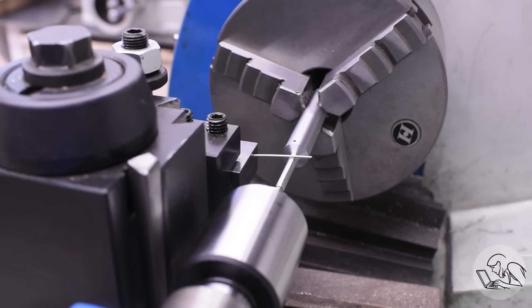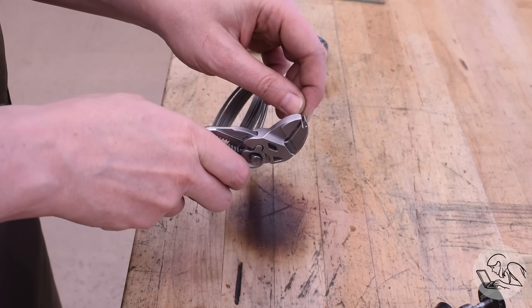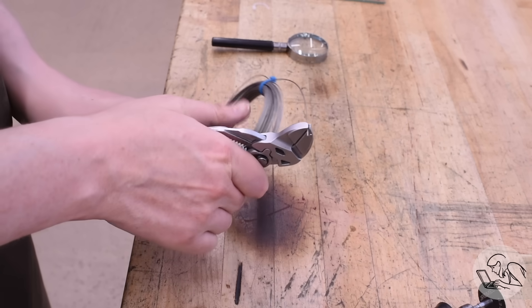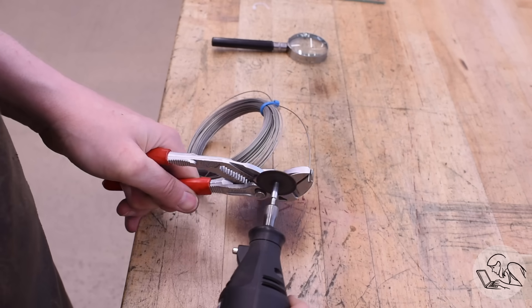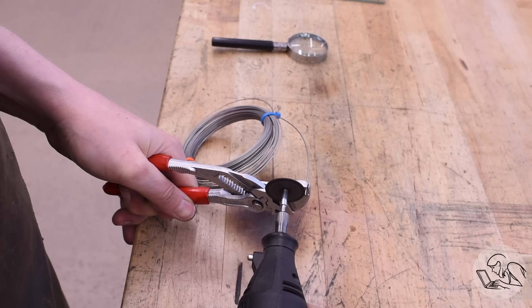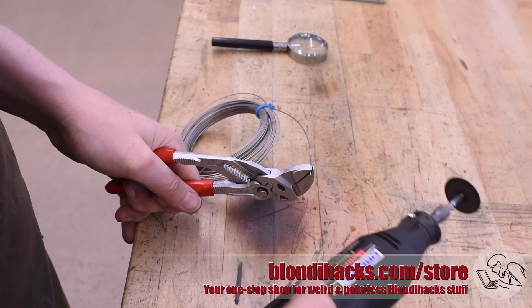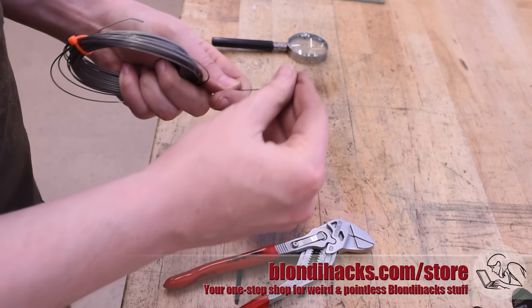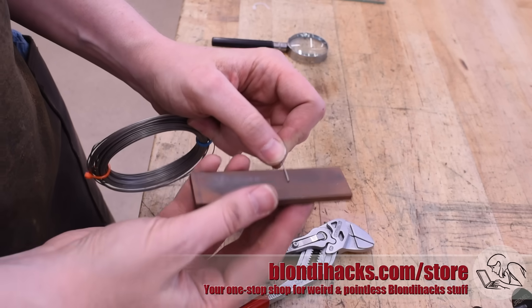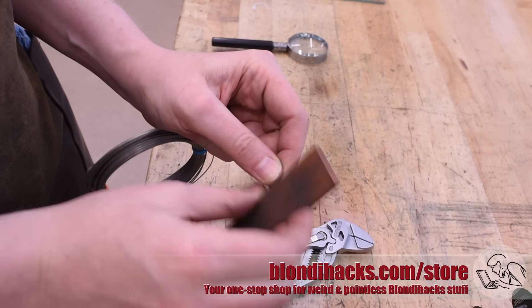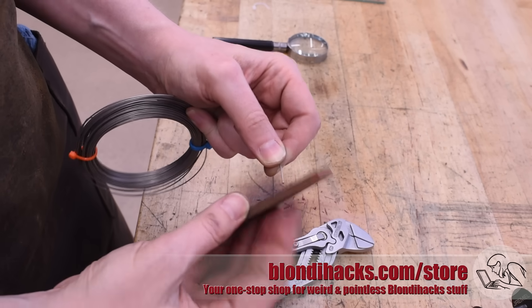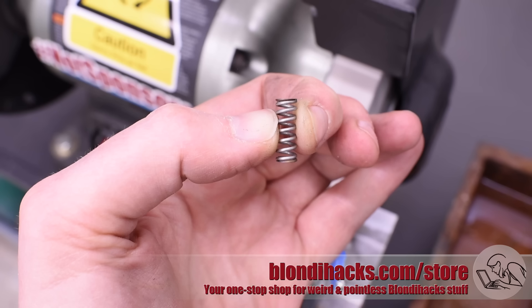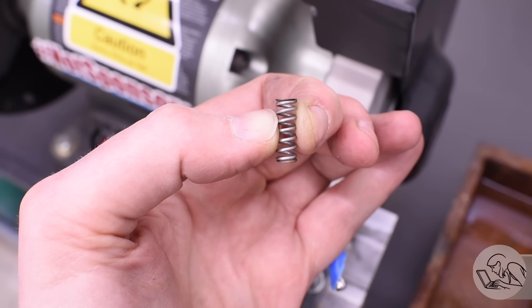Okay, it's time for wire. You really want to cut a section of wire to work with. Resist the urge to use the entire coil in this fixture. It'll never work. Those coils are very difficult to manage and if it sproings on you, you're going to be having a very bad day. To cut this stuff, you need to use grinding tools. Don't try to use nippers or any other bladed tool like a saw. Spring wire is very hard and you'll damage those tools. For the same reason, if you need to deburr it, use a stone and not a file. So cut off a piece of it a lot longer than you think you're going to need. The springs that I'm making here don't look like much but they actually have almost 11 inches of wire in them. So cut off a bigger piece than you think you need.